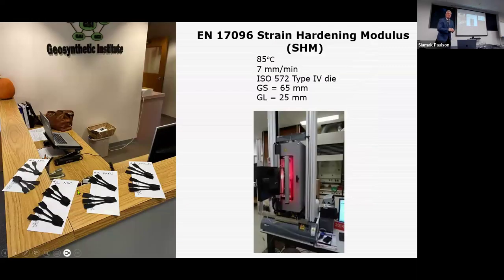The next one was, we can't wait that long, especially for the high grade materials. So why don't we move now to strain hardening modulus? It will at least give you some ability from a manufacturer quality control standpoint, if you know you're in the right house. Might not be in the right seat, but you'd certainly be in the right house. And this is strain hardening modulus. It's conducted at an elevated temperature on a continuous rate of extension machine. Very prescriptive way to run the test.